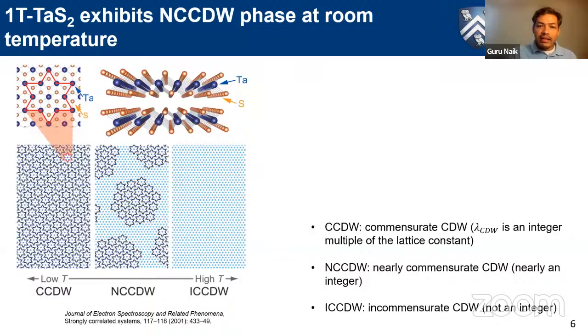And the second thing is a lot of the strong correlations often come at low temperatures, where the phonon interaction or the temperature-induced interactions are small. And that's where we see, for example, superconductivity, antiferromagnetism, etc. But in the case of tantalum disulfide, we see this strong charge density wave interaction happening at room temperature. So in fact, it supports two modes.